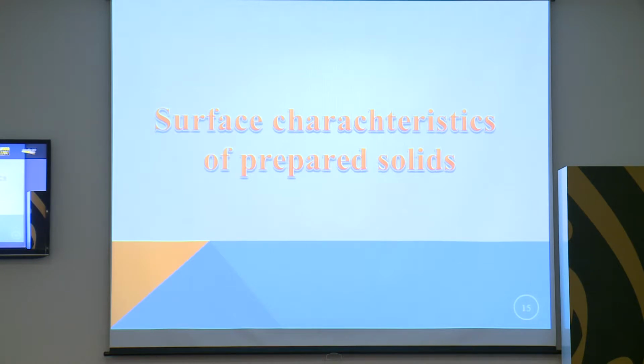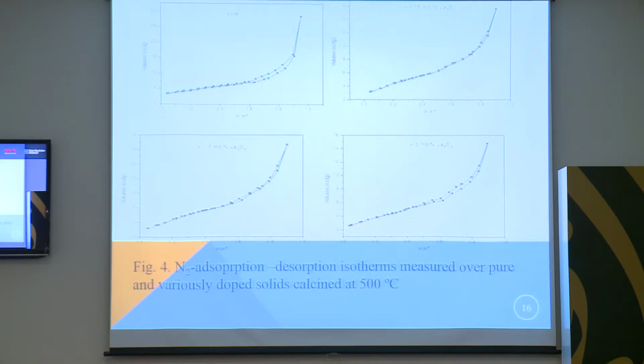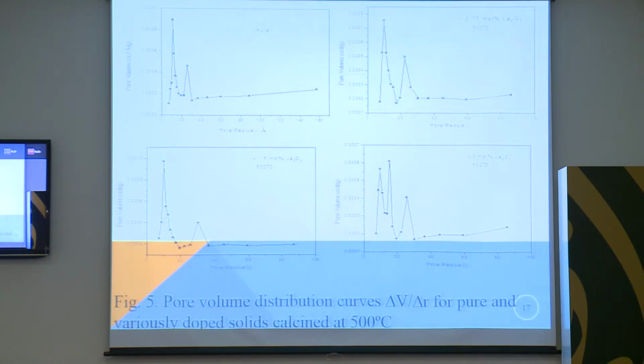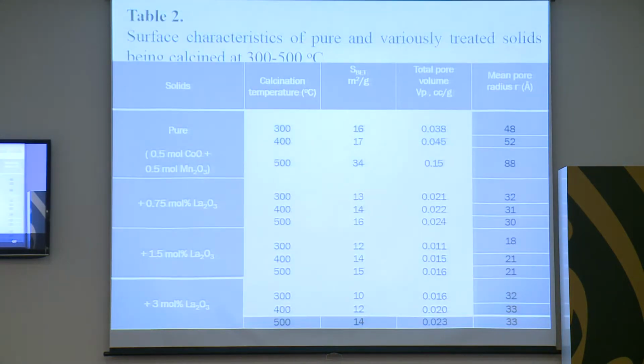In studying the surface characteristics of the prepared solids, nitrogen adsorption-desorption isotherms, measured over pure and variously doped solids calcined at 500 degrees, refer to an adsorption process of Brunauer type 2 classification with a small hysteresis loop. The pore volume distribution curve for pure and variously doped solids calcined at 500 refers to all the solids, pure and doped, exhibiting bimodal pore volume distribution, except the heavy load, which was a trimodal distribution.